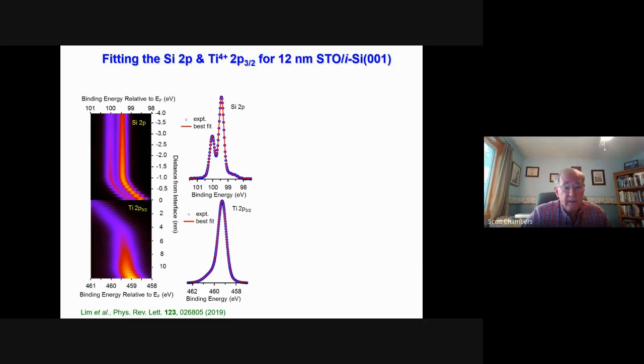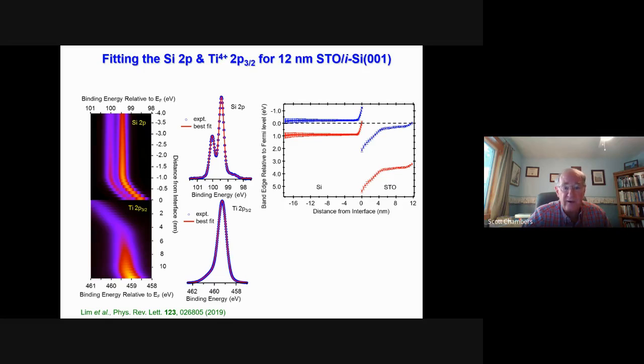Now, if we do that for the silicon 2p and the titanium 4+ component of the titanium 2p 3/2, what we get is shown here. You can see on the right, the quality of the fits is really good. And on the left, you see a heat plot, which shows the intensities for all the different layers, which when summed together give you that best fit over on the right. And then from those core level binding energy profiles, we can extract the band edge profiles for the system. And that's what we get. And so notice several things.